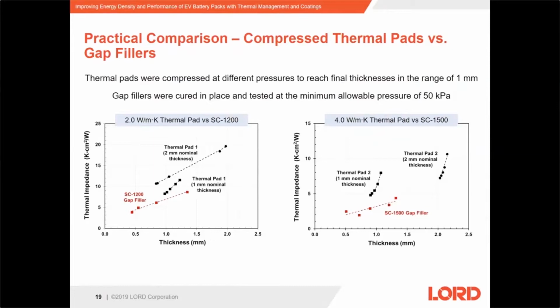And you can see that at the same thickness, the gap filler has a much lower thermal impedance than either thermal pad. The gap filler can also fill much smaller gaps than either the 1mm or 2mm pad can be compressed to. The graph on the right shows the 4-watt thermal pad versus the Therm SC1500 gap filler. And again, you can see the gap filler has much lower thermal impedance at the same thickness. You can also see that these 4-watt thermal pads were actually much more difficult to compress below their nominal thickness because they have much more ceramic filler in them. So they're going to be able to cover even less tolerance than the gap filler is able to.